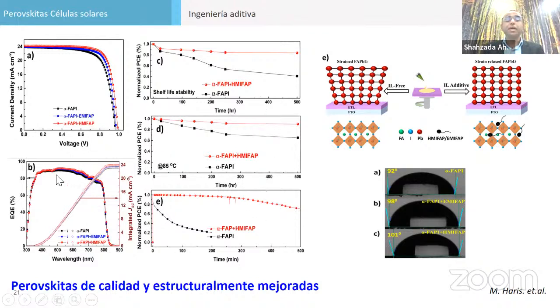This is the JV curve, and this is the EQE graph showing how many photons are converted into electrons. It's almost 85% in the visible region from 400 to 800 nm. We also monitored the stability at 85 degrees centigrade for 500 hours, and it was relatively stable. You can see that there.